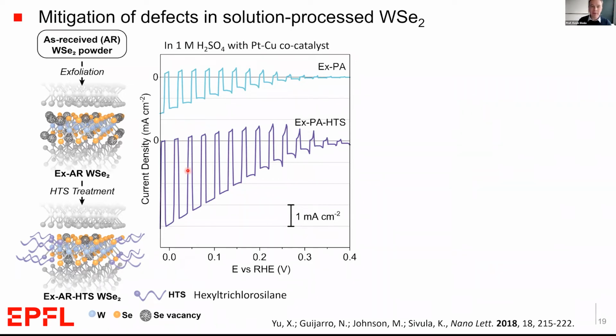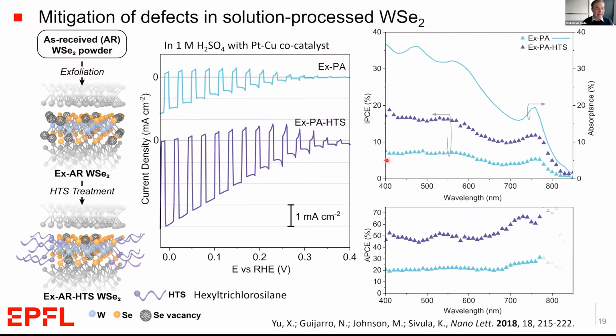But we have to remember that our flakes are extremely thin, only a few atomic layers, and we're not absorbing a lot of light. So if we account for that by looking first at the quantum efficiency, and the quantum efficiency normalized to the amount of light being absorbed, that's the absorbed photon to current efficiency here as a function of wavelength, we can see that closer to 600 or 700 nanometers, actually we're getting about 60%. That was the same as the single crystal.